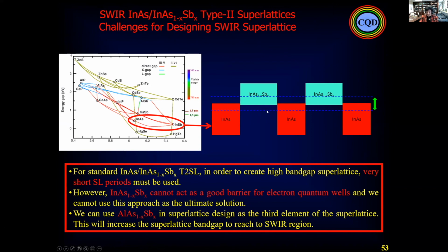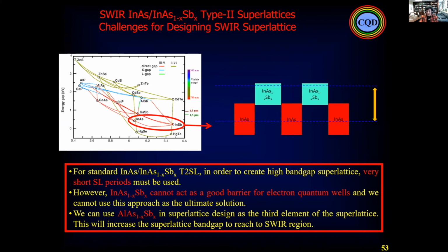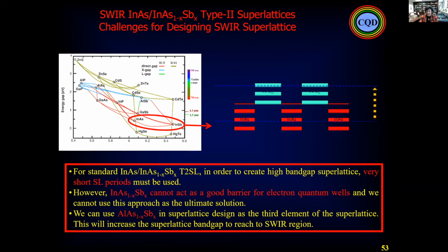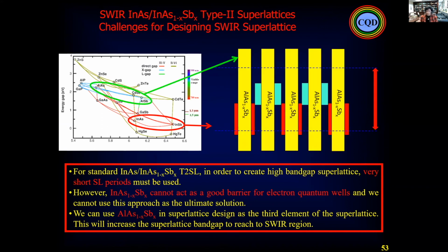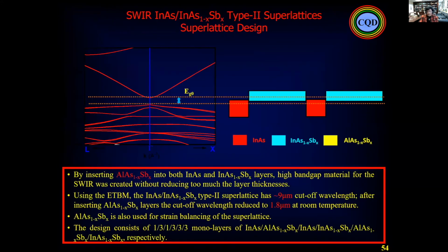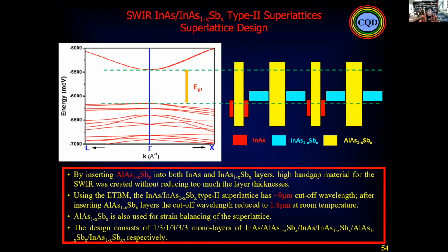And by changing again with the gap engineering, we can have not only different wavelengths, but at the same time come with the barrier to have the material that can go from 0.5 micron, the visible, the UV, up to the terahertz with excellent performance. And exactly as you can see here, by doing the atomic gap engineering of the 3-5, we can again change the gap, as an example, for the 9 micron, by putting a little barrier, we can go to 1.8 micron or even less than that.